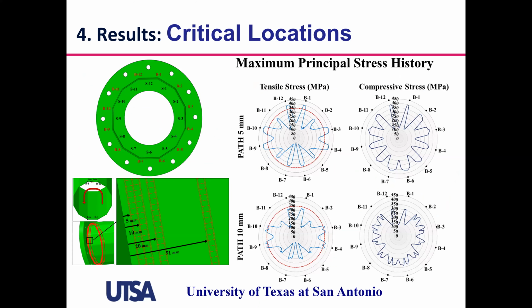Then from our simulations, we were able to extract the stresses along a path of the pole, and we considered different distances from the base plate. And here you see radial stresses that show the tensile and compressive stresses through this path. So here it's at 5 millimeters and at 10 millimeters. As you get closer to the base plate, the stresses are higher.